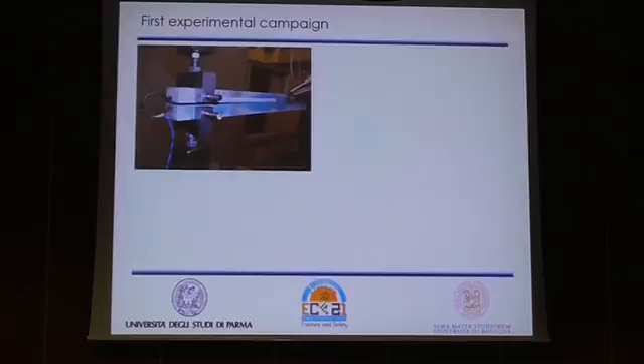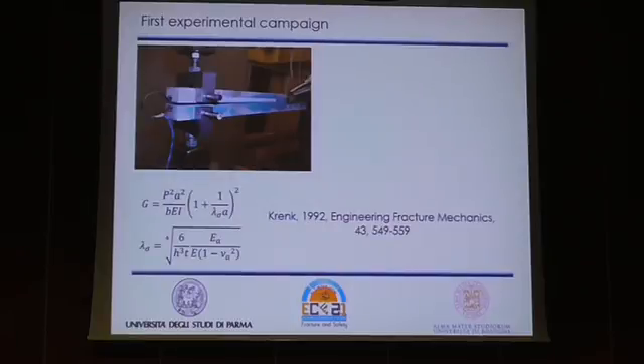Since the pre-cracking phase, we noticed that there was a decrease of the energy necessary to make the crack propagate in the nanomodified specimens with respect to the virgin one. DCB tests were performed applying a load-unload law in order to obtain in the declining part of the force displacement curve some reload sections with a constant slope, which allows to evaluate the specimen compliance and therefore the actual crack length. The values of the strain energy release rate were evaluated using the Krenk model, including the parameter lambda used for the correction that the crack required.